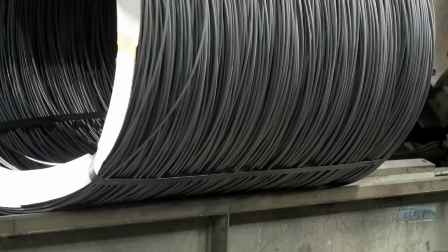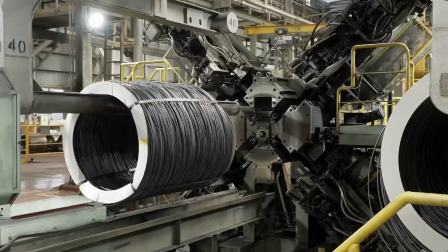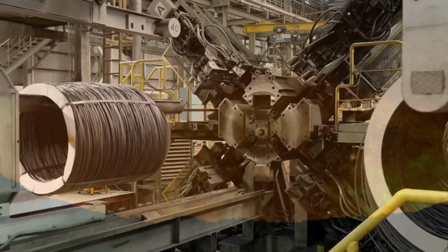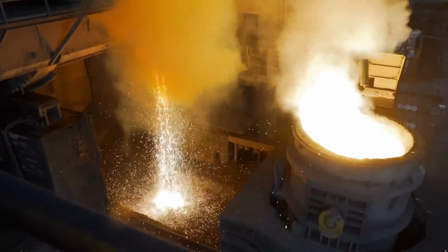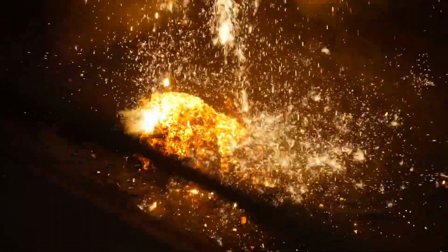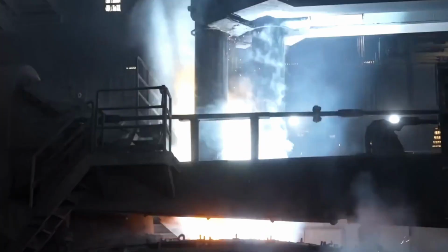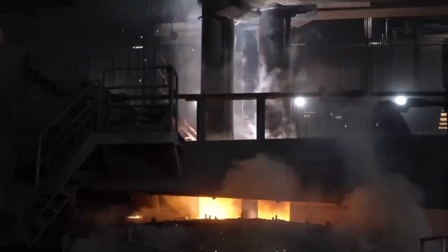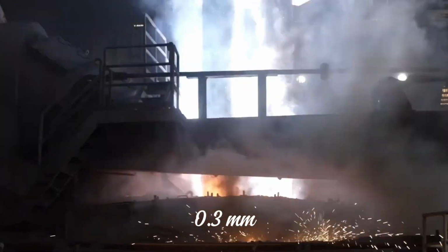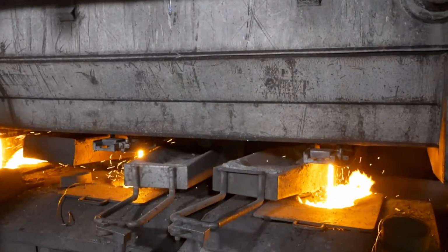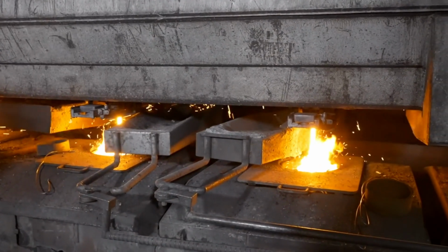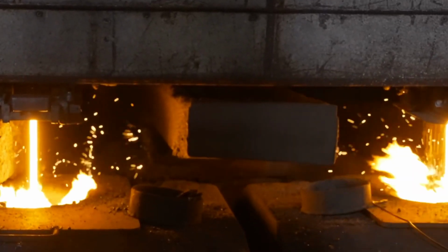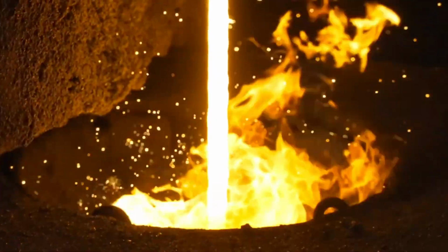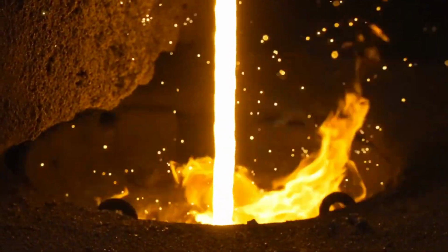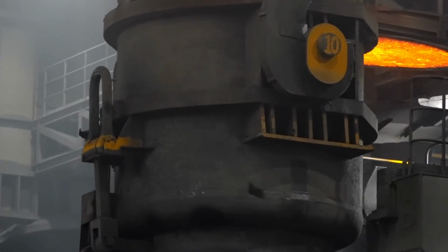The slab is thinner, but not yet flat or dimensionally accurate. That precision forms only inside the finishing mill. What happens when thickness drifts by 0.3 millimeters? Laser sensors scan every millimeter from above and below. Target tolerance, plus or minus 0.1 millimeter across plates up to 30 meters long.